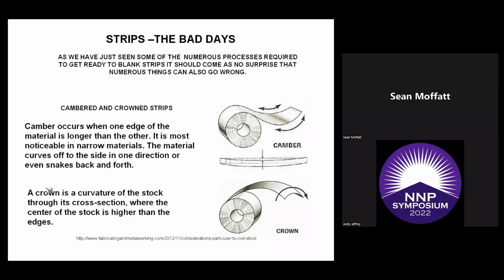Camber occurs when one edge of the material is longer than the other, and it's most noticeable in narrow materials. The material curves off to one side in one direction. It can even snake back and forth. If you took a strip with a bad camber and laid it out on the ground, like out in the parking lot, uncoiling it, it would go around a big circle eventually. And for a crown, there's a curvature in the stock that makes it thicker in the middle, for whatever reason, so it makes it tight to fit.